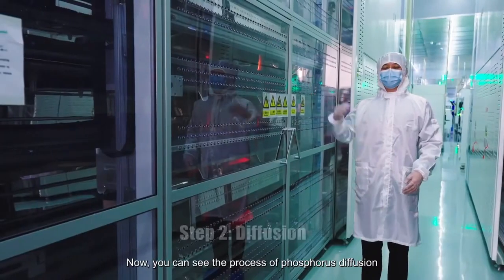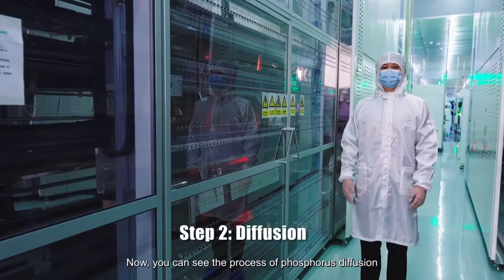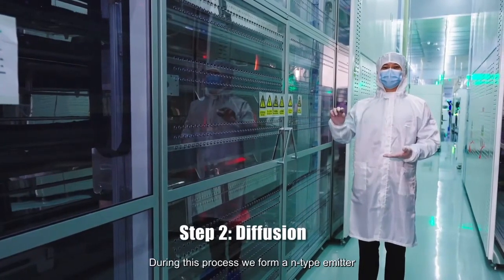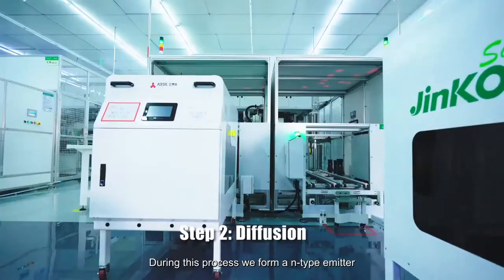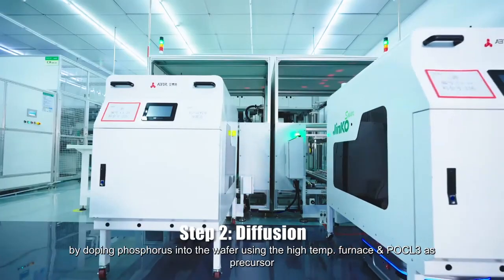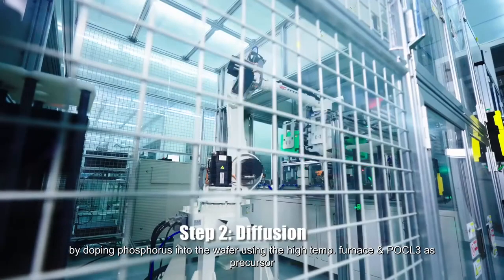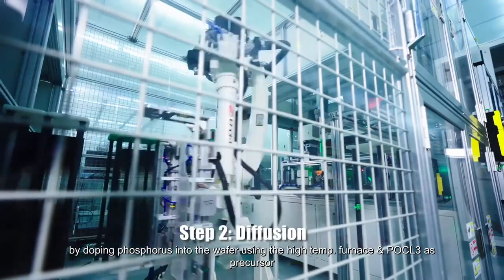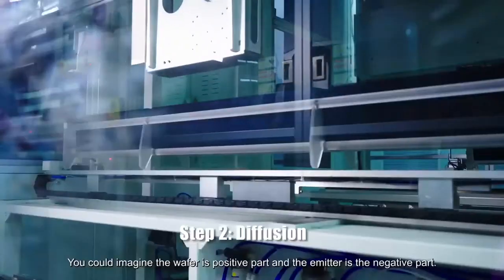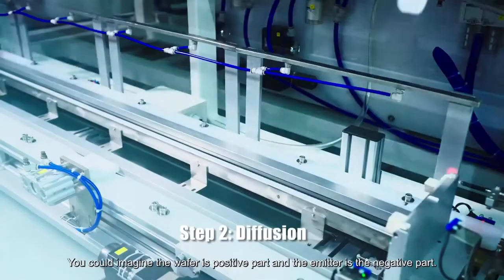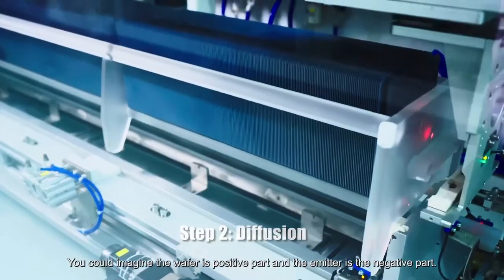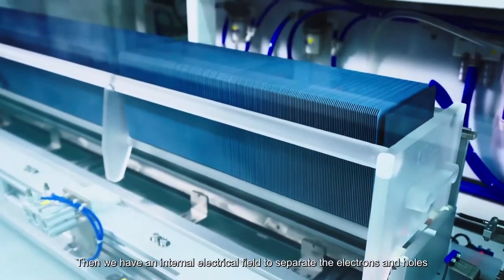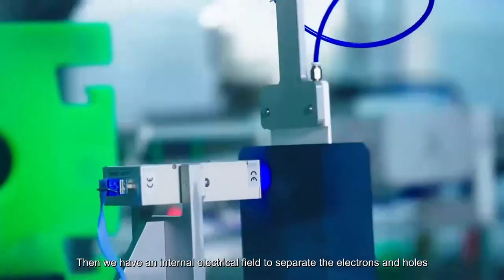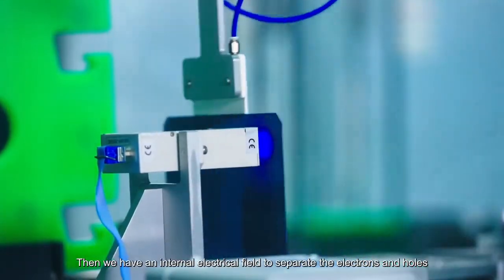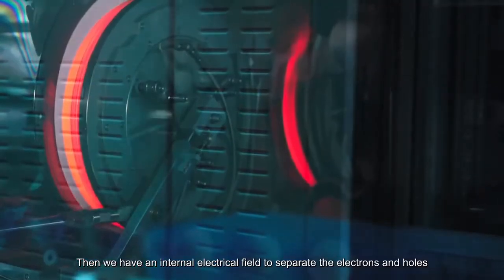Now you can see the process of phosphorus diffusion. During this process, we form an N-type emitter by doping phosphorus into the wafer, using a high-temperature furnace and POCl3 as precursor. You could imagine the wafer is the positive part and the emitter is the negative part. Then we have an internal electrical field to separate the electrons and holes.